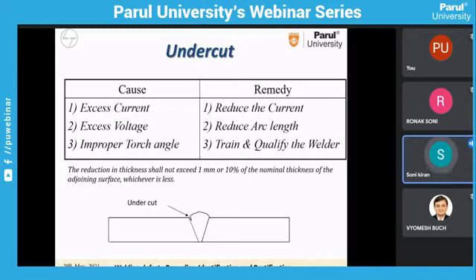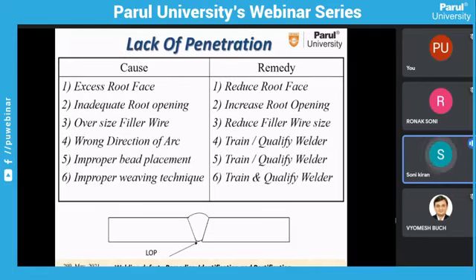A small undercut will always be there because of welding, but for excessive undercut there is a criterion: 1 mm or 10% of nominal thickness, whichever is minimum, is allowed, but more than that is not allowed. So the boundary line between discontinuity and defect is this. The cause is excessive current or voltage, and we prevent it by lowering the ampere.